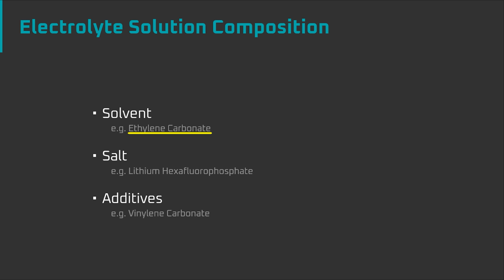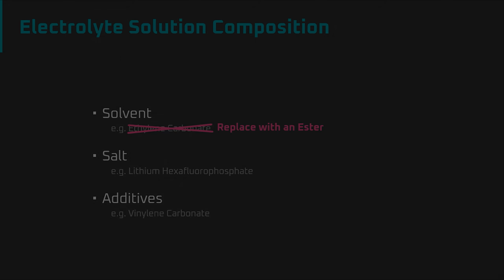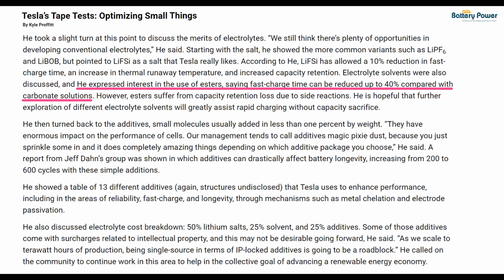One of the best ways to reduce the viscosity of the electrolyte and increase the charging speed is to swap the carbonate-based solvent for an ester-based solvent. Engineers from Tesla have said that by switching to an ester-based solvent, charging speed can be increased by 40%. But Tesla doesn't use those esters because they can negatively impact cycle life. So how did CATL get around the cycle life issue?